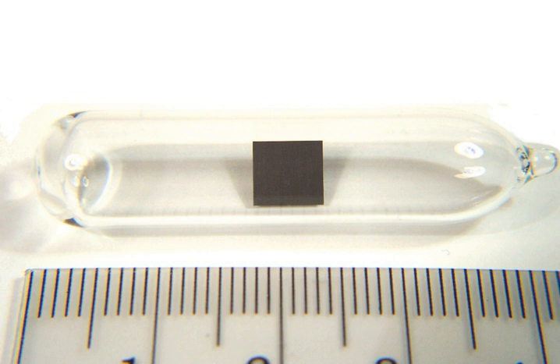During the production of incandescent filaments, recrystallization of tungsten is significantly lowered by adding small amounts of thorium dioxide to the tungsten sintering powder before drawing the filaments. A small addition of thorium to tungsten thermocathodes considerably reduces the work function of electrons. As a result, electrons are emitted at considerably lower temperatures.